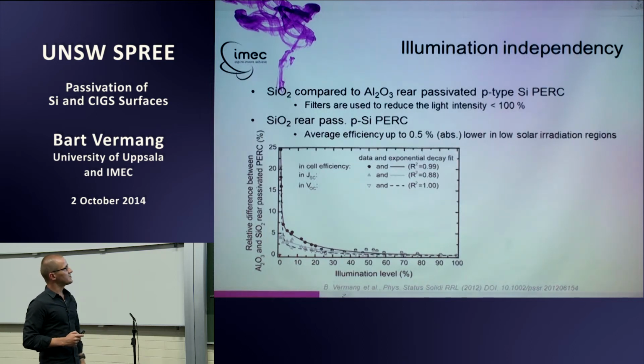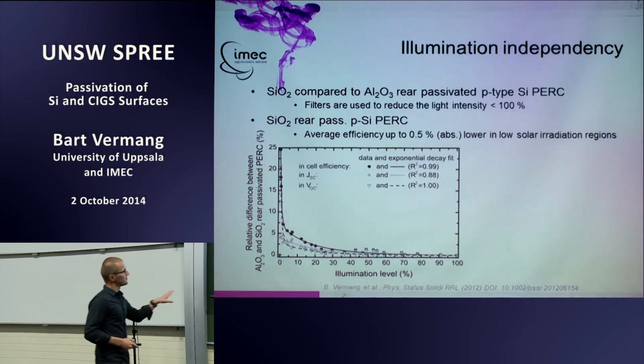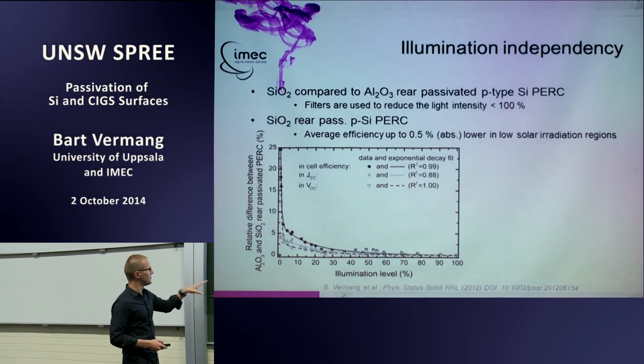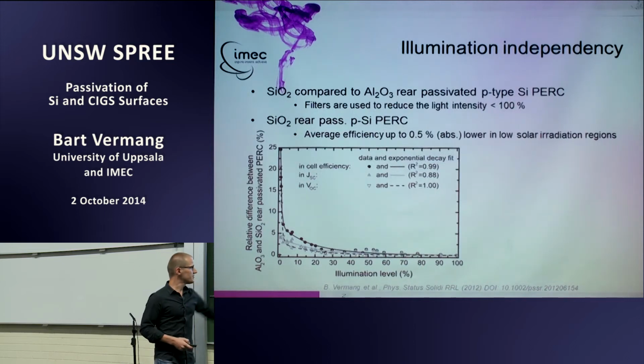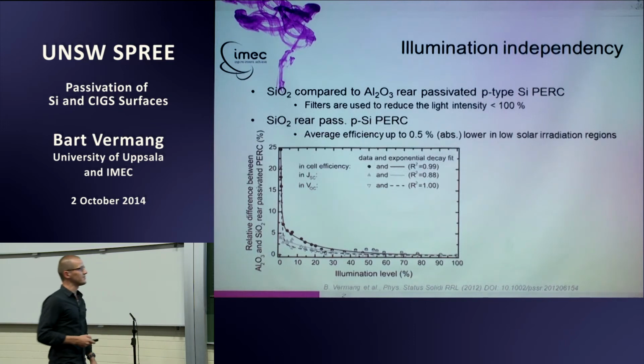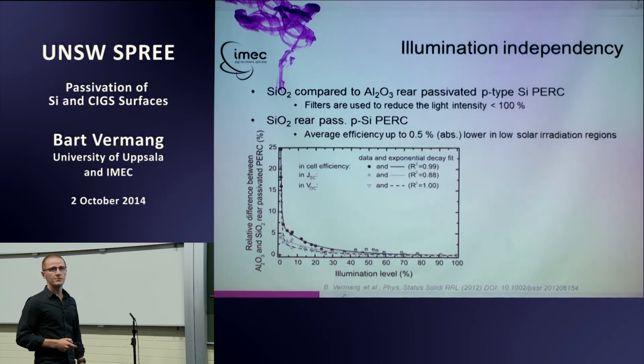And we even made a calculation for lower solar irradiation regions, like for example Belgium. And on a yearly basis, you can lose up to 0.5%. So your average efficiency is not 19.5 or 20.5 anymore, but your average efficiency becomes 19 or 20. So you lose up to 0.5% for your cell. I didn't mention it, so typically for this part I will really not go in detail, but I always put the papers at the bottom of the slides so you can have a more detailed look. And I can also share the PDF after the presentation so you can have a more detailed look as well.